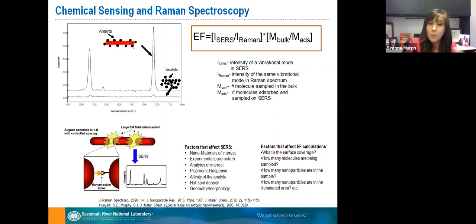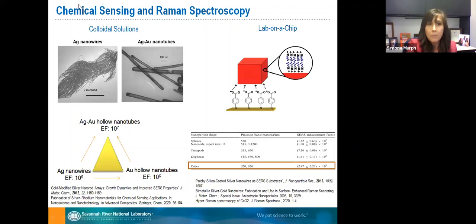So we did a lot of basic science with model analytes to really understand the systems that we have. It's also important whether you do this measurement in solutions or you do lab on a chip. You can see here an example, for example, silver nanowires versus the gold silver nanotubes. We found that the gold silver nanotubes produce an enhancement factor of 10 to the 7, and they were better than the silver nanowires, even though they have different plasmon bands. The gold silver nanoparticles were closely matching the 633 laser line that we use. And also here an example that I just mentioned, if you have the cubes versus the spheres or the rods, we got a better enhancement response than having just the spherical nanoparticles. And of course here, this is attributed to the hotspots for the structures.